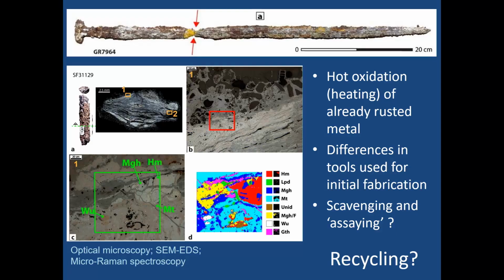Ivan's work has been truly amazing in trying to pull out the microscopic differences in iron oxide phases in these entirely corroded samples. And what he's been able to find is evidence for the reheating of these artefacts after they were already rusted and deposited in the ground, different tools that were used for their final recycling as opposed to their initial fabrication. It looks as though someone was coming to the site, scavenging this material and assaying it, knocking it about to see if there was any good iron left in it, and then taking it away.